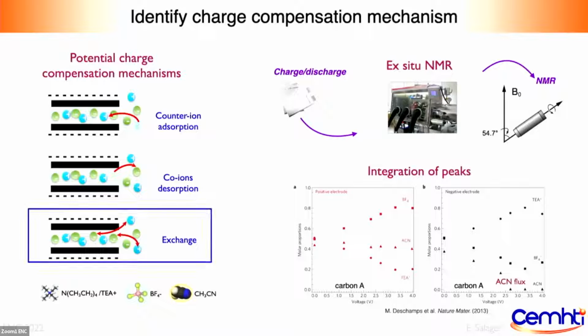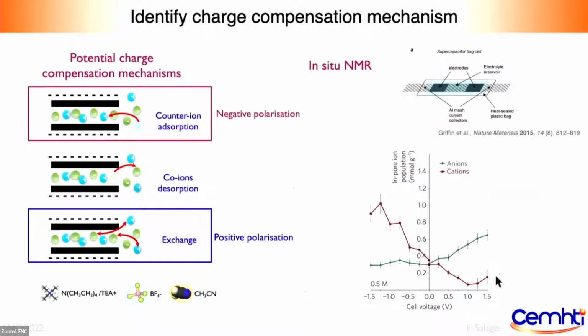And so ex situ, what was identified was exchange, but there was something a bit weird at the negative electrode, that the acetonitrile would also move in the process. And so there was the question whether this was an ex situ NMR artifact, because the acetonitrile can evaporate so easily, or whether it was real. There had been another study 2 years later by John Griffin and Alex Forse in Clare Grey's group, where they identified a slightly different mechanism with a bigger proportion of counter-ion adsorption. But again, that was not the same carbon. It was a phosphonium instead of an ammonium, and they changed the geometry.